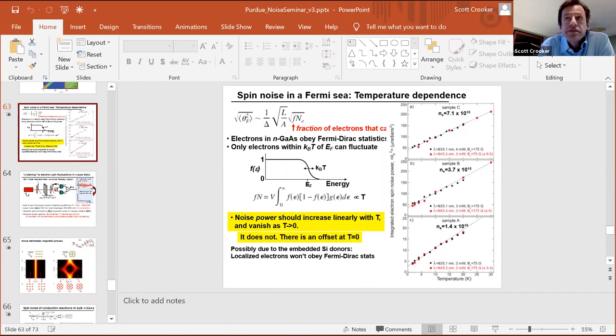No, let's see. The lowest we've gone using this technique is about 1.5 Kelvin, with the sample in superfluid. I think folks in NMR would probably argue that some of their measurements could be classified as noise measurements, and those are certainly done in helium-3 refrigerators down to hundreds of millikelvin. I think they'd have a legitimate claim for that. But of course, that's a completely different method, just using pickup coils or SQUID magnetometers. How high a magnetic field can you go? At the moment, we've gone up to 7 Tesla, just in an optical cryostat.